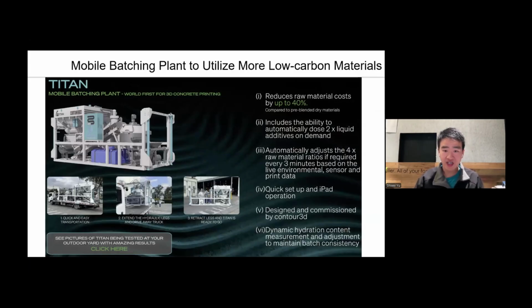And we also developed our own mobile batch plant designed specifically for 3D concrete printing. Up until now, we have mostly relied on ready-mix dry material in bulk bags, but this approach limits us because most of the raw material like sand or crushed dust arrives in a wet state. To use it in a dry mix is very hard, and drying this material is very carbon intensive. Our new batch plant solves this. It has 4 separate silos: one for crushed dust, one for sand, one for cementitious materials, and one for the master batch, which is our additives and the fibers in our mix.